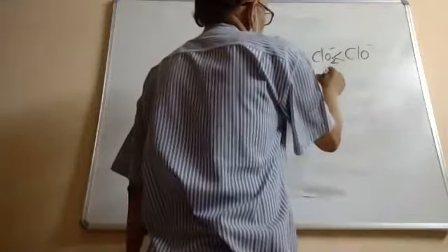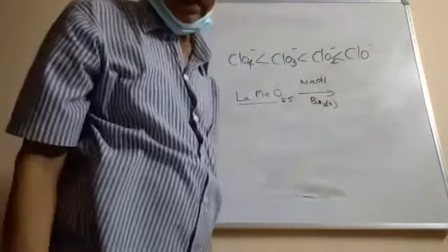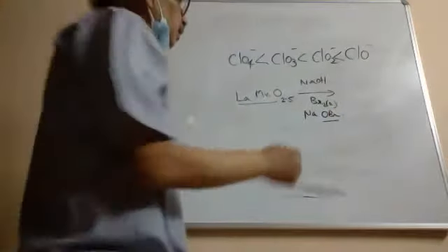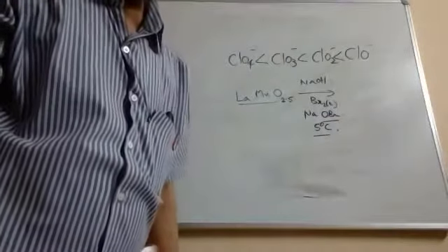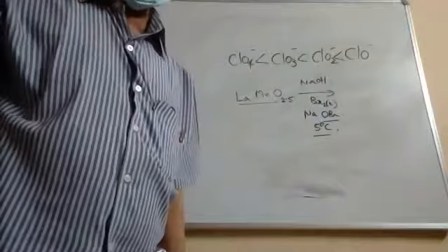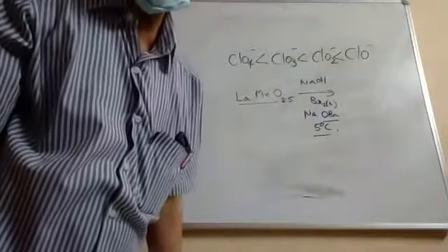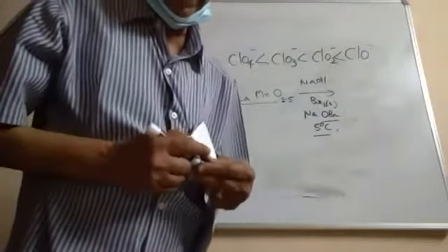So if you want to really oxygenate them at low temperatures, what you do basically is you take sodium hydroxide and liquid bromine. What happens here is the sodium hydroxide reacts with the bromine to make what we call sodium hypobromite. These reactions are carried out at 5 degrees Celsius, very low temperatures. So you don't need very high temperature furnaces here for oxygenation. These are what we call in French, chimie douce, that is soft chemistry.